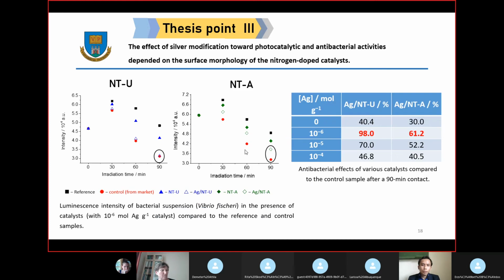The antibacterial activity shows that, compared to the control which was obtained from the market, the silver N-TiO2 catalyst at this concentration is relatively similar to the control. However, for the NTA it was smaller compared to the control. But both silver modifications proved to enhance the antibacterial activity compared with the unmodified one.